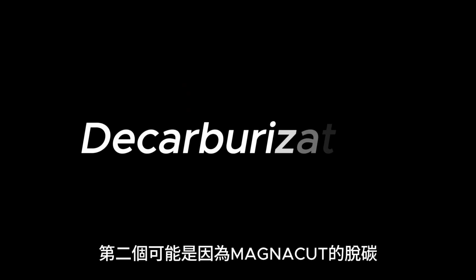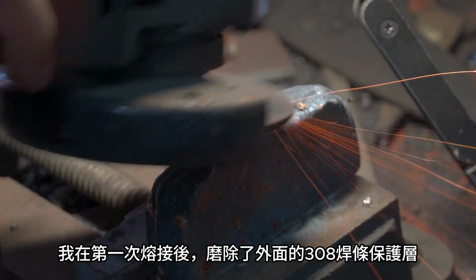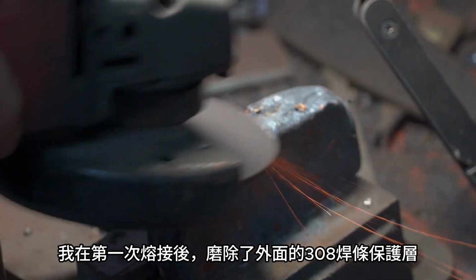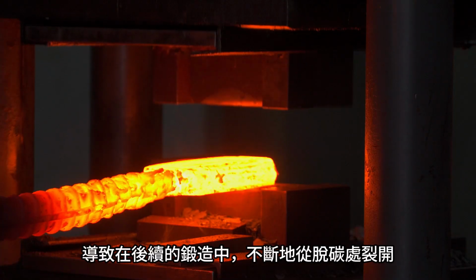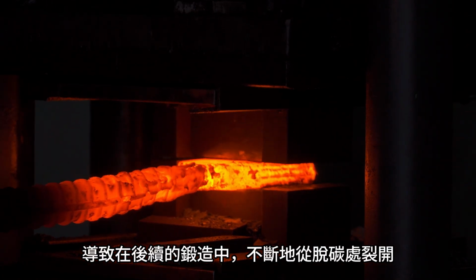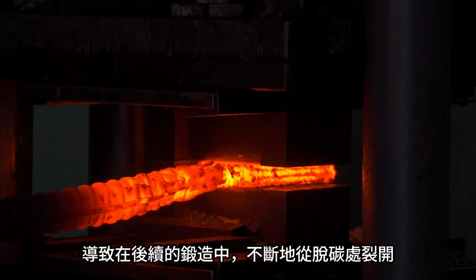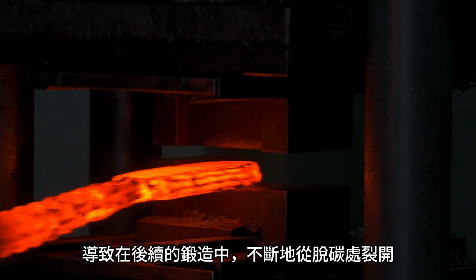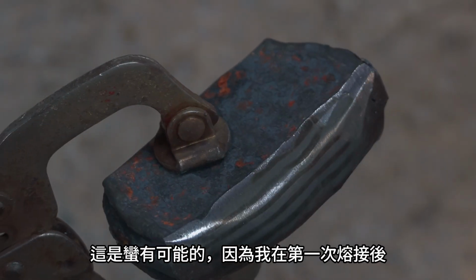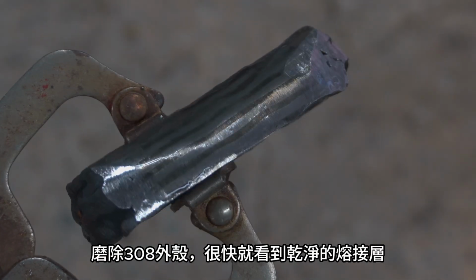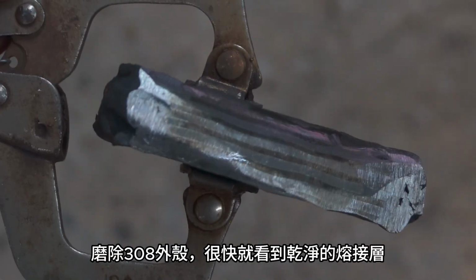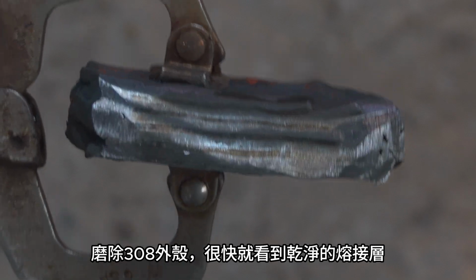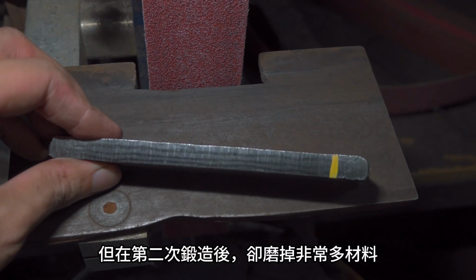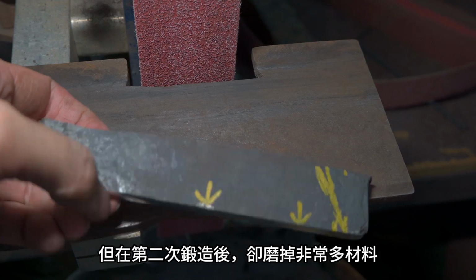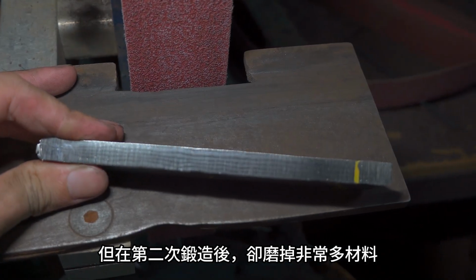The second is decarburization of MagnaCut. After the first forge weld, I ground off the protective 308 welding rod shell, which may have led to continuous cracking from the decarburized area during subsequent forging. This seems quite likely because after the first weld, I quickly reached the clean weld layer once I removed the 308 shell. However, after the second forging, I had to remove a considerable amount of material.